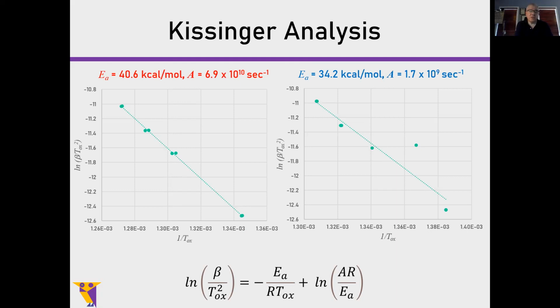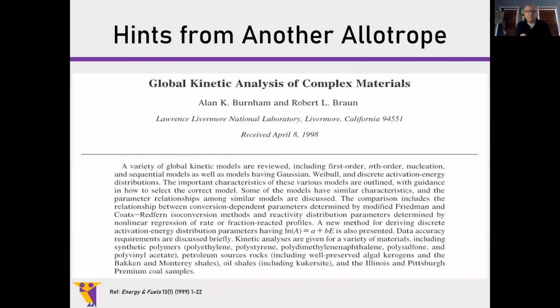I can tell how much of them there are, and I can tell something about their properties by at least how they operate, how they interact with air. I can find that they have different activation energies, and if I plug these into a simple kinetic equation, I can get the prefactor. So I can see a little bit about each one of these being slightly different from the other, even though the ad on the box said that this is a homogeneous material. It isn't, at least in terms of composition. What else can we learn from TGA?